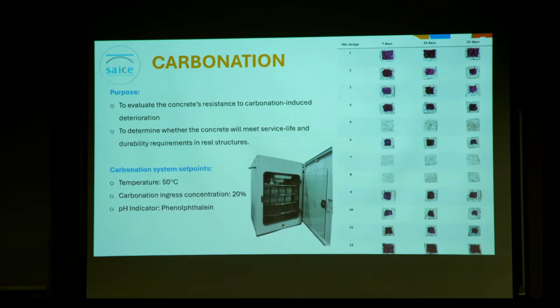In my results, the highly replaced mixes underwent full carbonation in comparison to the reference mix, Mix 12. However, it is important to note that carbonation simulates decades of penetration, often equivalent to more than 20 years. This allows us to meaningfully assess a long-term structural durability performance indicator over a shorter time frame.